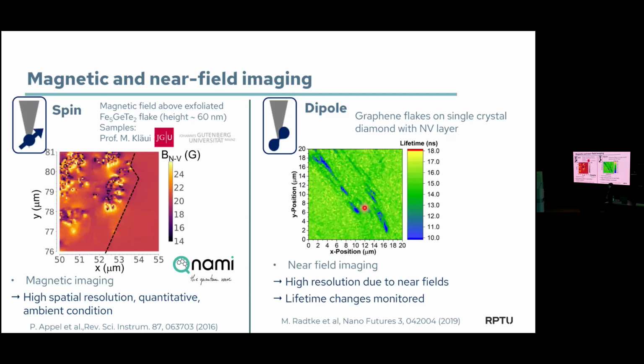When we would do this with the scanning tip, we would also end up with a resolution that is on the order of the distance of your NV to the sample. So this would be roughly the same as in the magnetic images. Of course, if you're really working in the same molecule, then you get even better resolution. But in the end, also here, it will be limited by the question, how close can I get the NV to the sample? This is more or less the limiting factor also here.